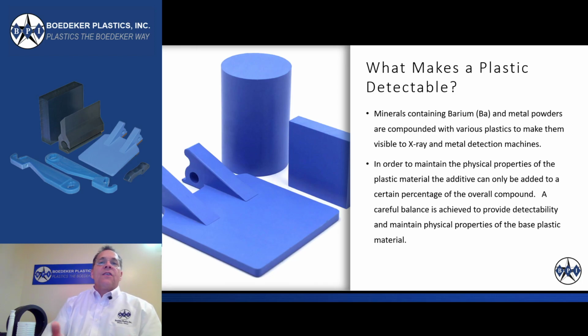Now the key here is the actual level of additive that's put into the product. You need enough material to make the material detectable, but you don't want enough filler that you compromise the integrity of the material itself. Too much filler can actually embrittle the material and make it more prone to breakage. So it's really a critical balance as to how much filler you put into these products.